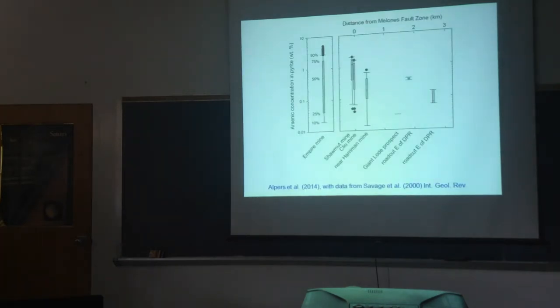I took that same data and compared it to Empire Mine, and I changed it to a logarithmic scale here. And so you can see, again, the increasing arsenic as you get closer to the Melones Fault. And then the overall distribution of arsenic in pyrite at Empire Mine kind of spans the full range of this. And in Empire Mine, again, we're not associated directly with the Melones Fault. It's a more dispersed type of mineralization with a number of different structures. And so the relationships are not quite as simple, but we definitely have that full range of arsenic in pyrite, from less than a tenth of a weight percent up to several weight percent in some of the outliers.